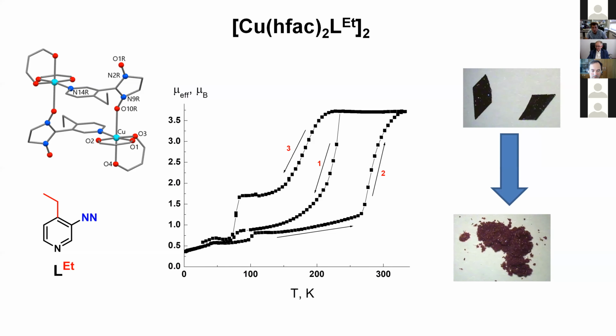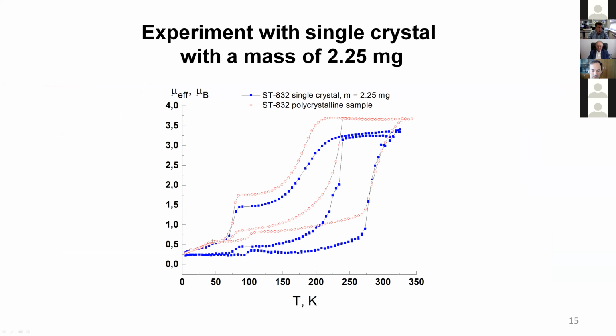Compared with the first cooling, the decrease of the magnetic moment in the region 150 to 220 occurs more smoothly, and the amplitude of change is smaller, while a sharp decrease in the region of 65 and 85 Kelvin persists, and its amplitude increases. Below 65 Kelvin, the value of the magnetic moment is 0.7, and slightly decreases with further cooling. If we take a single crystal with a mass of 2.25 milligram and do the same measurements, we will see that the temperature dependence of the magnetic moment is similar to that of a polycrystalline sample.